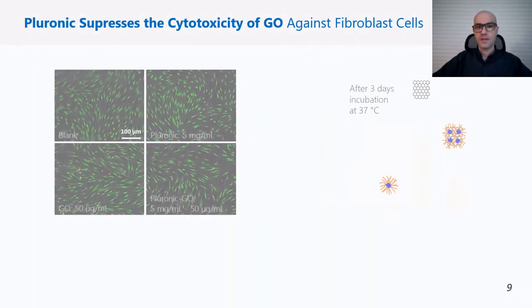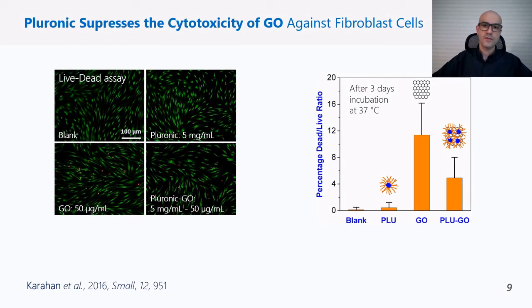And very interestingly, the mixture of pluronic and graphene oxide showed lower toxicity to human skin cells. Under the experimental conditions we studied, graphene oxide killed around 12% of the cells, while the combination of pluronic and graphene oxide killed less than 6%. This observation is a bit puzzling, but mammalian cells are known to be jello-like substances, and they have extra support of a microtubular cytoskeleton, so we think that they might be handling the osmotic pressure effects a bit better.